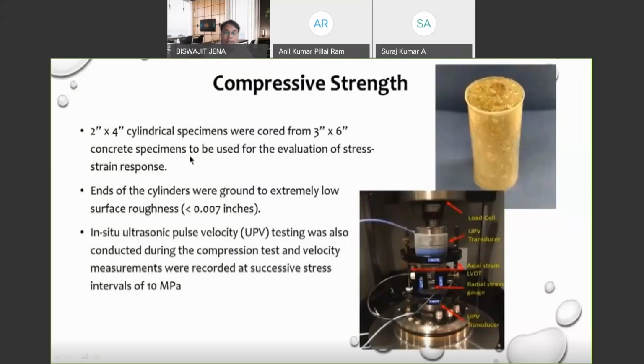If you just do a simple compressive strength test, we'll say that I have 150 or 160 megapascal strength. But like I showed you earlier, the reason why we use ultra high performance concrete is not just for strength. Strength is one thing, but we also want to know how we can use this material in designing the structures. So if you do the design of reinforced concrete structures like bridges or girders or columns, you actually want to know the complete stress strain response and the lateral response. So now the testing has to account for both the axial deformation and the lateral changes in dimension. So you have to measure both properties, like axial and lateral strain.